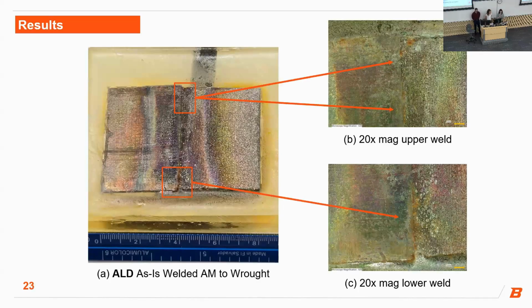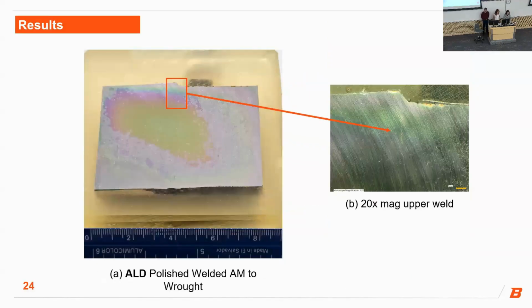Here are some images of our ALD as-is sample. The images on the right have very apparent corrosion in various locations along the weld. It's that classic rusty color. And we also see apparent damage in our ALD polished sample. It's more faint, but it's along the weld at the very top of the sample. It kind of looks like a thin white line. And these physical results correspond with the limited EIS data that we were observing. This decrease in resistance we think is likely due to a non-uniform ALD coating at the weld because of the weld having heat-affected zones, internal stresses, and compositional gradients.